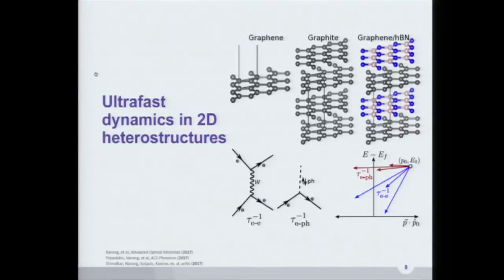And actually, that impacts the lifetimes in graphene, particularly in this graphene-HBN case. So it's not just that HBN makes graphene chemically inert. It does that. Yes, it keeps the gunk away from graphene, but it also adds this additional component of dealing with the phonon modes. And this is something that then got us excited to think about the twisted case. Of course, Pablo and others have given talks at CIQM about this, and we're now trying to think about how the lifetimes change fundamentally as a consequence of the layer mismatch.